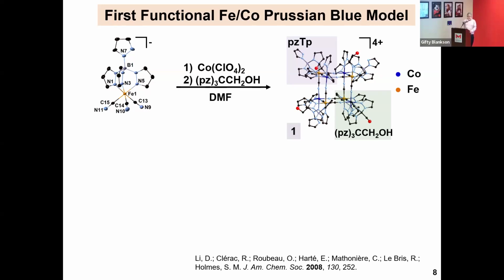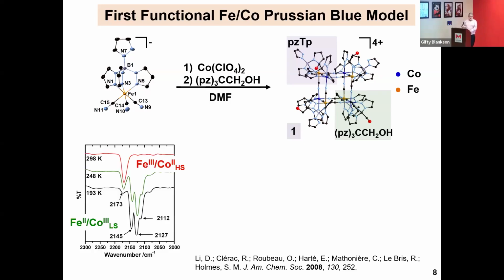We had to choose hydrogen bonding on the cobalt site because anything with an alkyl group would co-crystallize in the same manner as the iron. We couldn't differentiate the iron and the cobalt. So we had to take advantage of intermolecular hydrogen bonding between that terminal alcohol and its neighbors and lattice solvent to actually get a good X-ray structure. In other words, if you don't have a good X-ray structure, you don't get published. Right? So this is what the molecule looks like.